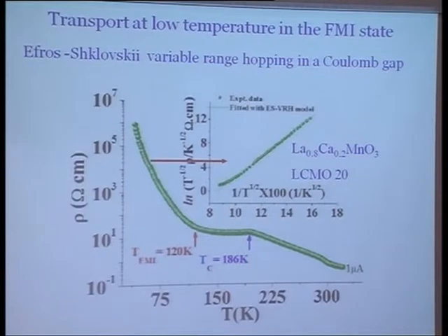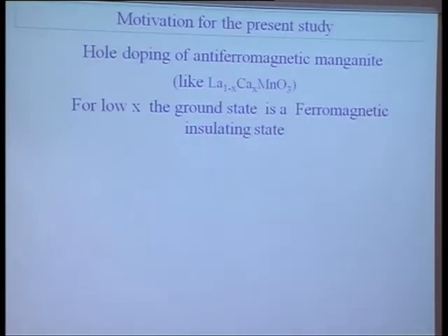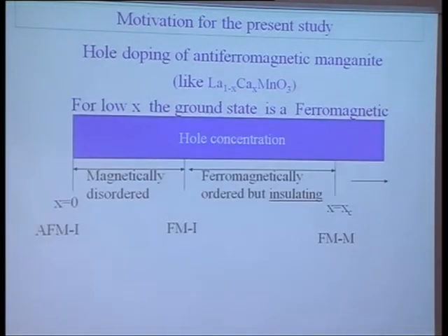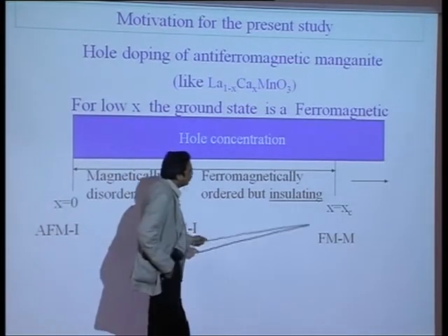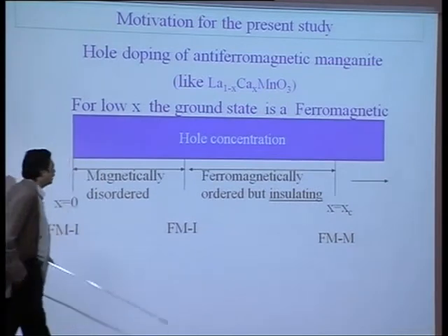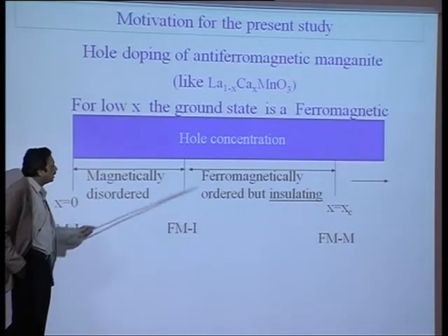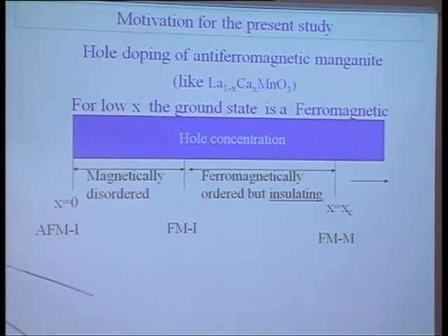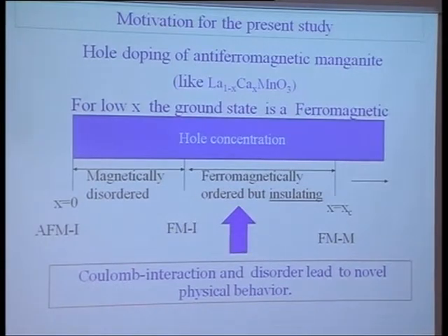So we say that, listen, we may be having variable range hopping in the Coulomb gap, and that is a signature of the type of system one is talking about. Now let me take this problem and put it into a very simple phase diagram, nothing much complicated. I started with the antiferromagnetic insulator, and at this critical composition I ended up with the ferromagnetic metal. In between, at some composition, the ferromagnetic state becomes stable, but it is still an insulating state. So it is this particular composition range one is talking about, and this is where the Coulomb interaction and disorder can play a very important role.